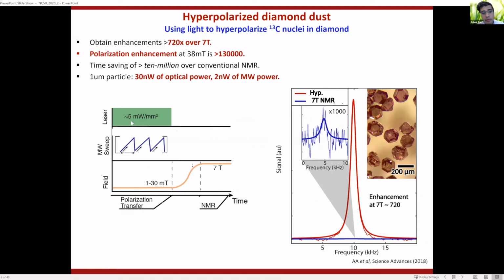But what it involves is a continuous irradiation of laser light, fairly low in power, and a chirped microwave excitation. So this is time on the x-axis and microwave frequency on the y-axis. So you're chirping the frequency of the microwaves at low magnetic field. And we then carry the sample to high magnetic field, as a control experiment, so you can see how much of the spins are actually polarized when you transfer them to a magnet.